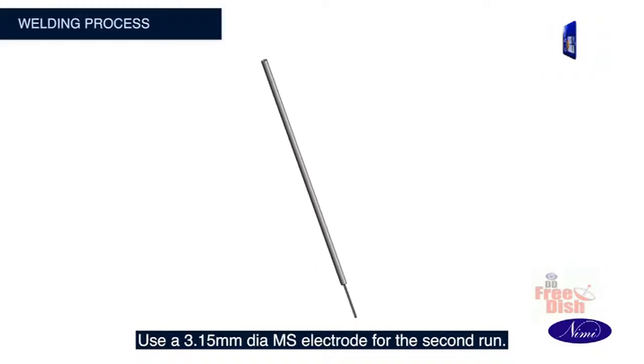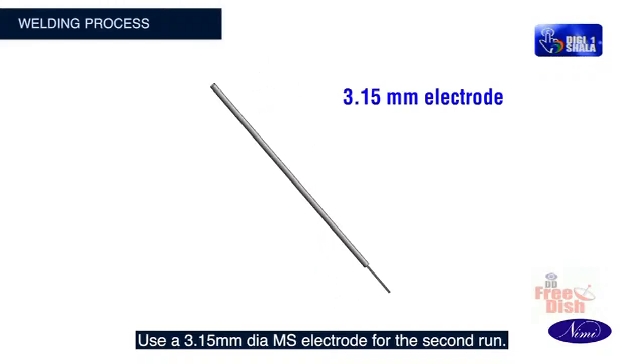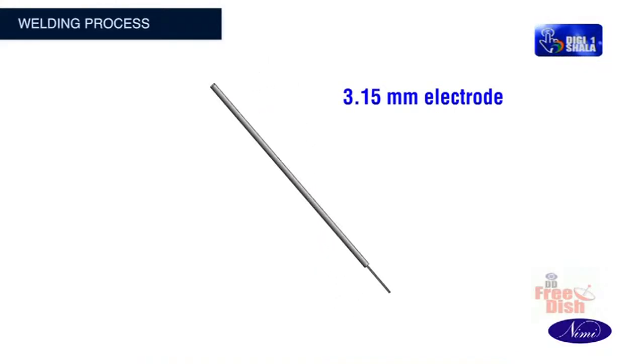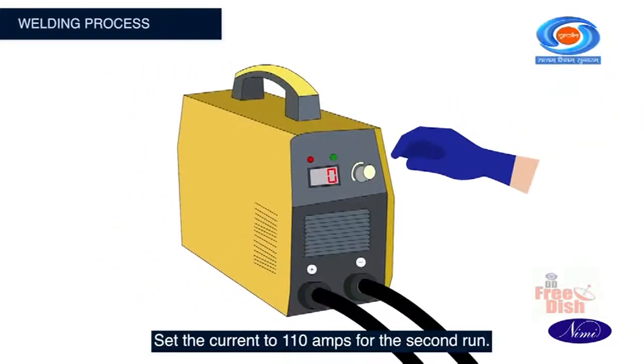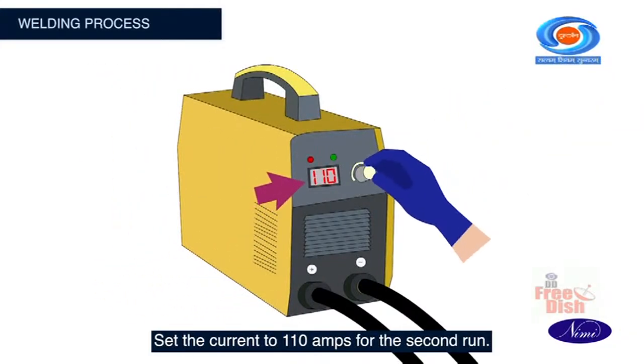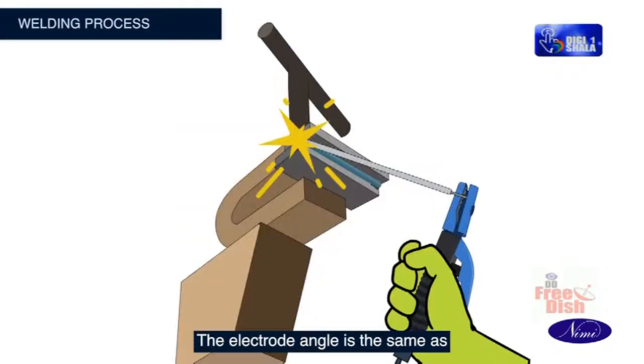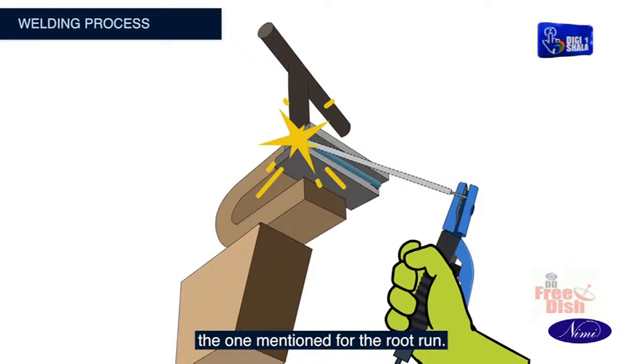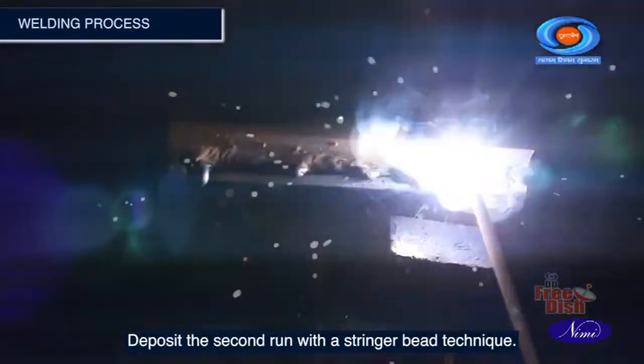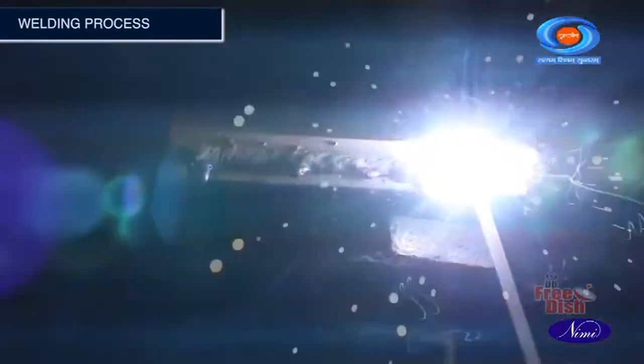Use a 3.15 mm dia MS electrode for the second run. Set the current to 110 amps for the second run. The electrode angle is the same as the one mentioned for the root run. Deposit the second run with a stringer bead technique.